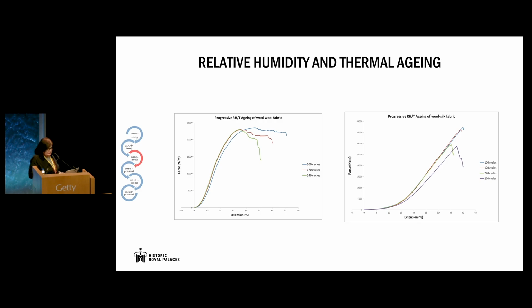Also, when we look at the stiffness, silk weft samples showed contrasting behavior to the wool ones. So this potentially could be attributed to chemical variations, as silk degradation causes breaking of the peptide bonds, converting a larger portion of the fiber into an amorphous region, which is less stiff. However, for the wool fibers, the primary effect of aging is that the disulfide bonds are converted to rigid cross-links, which effectively lock the fiber structure in its place, so it's making it more difficult to extend.